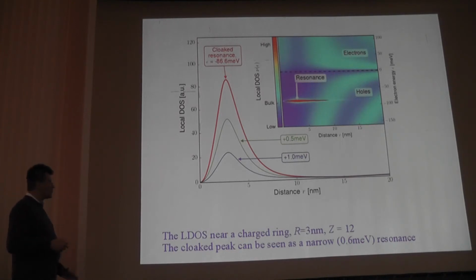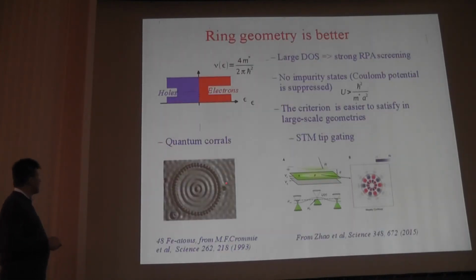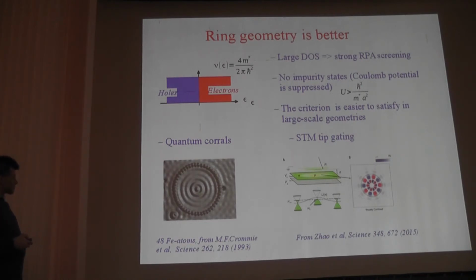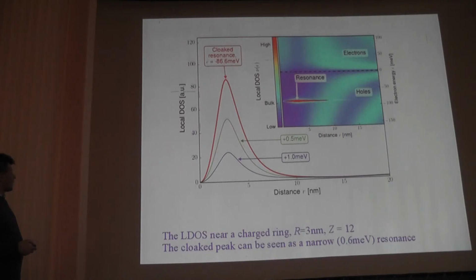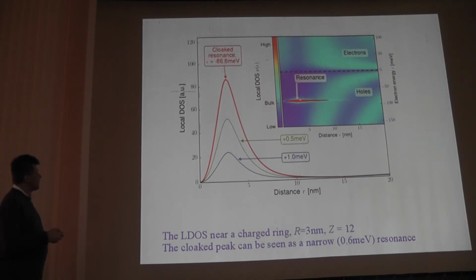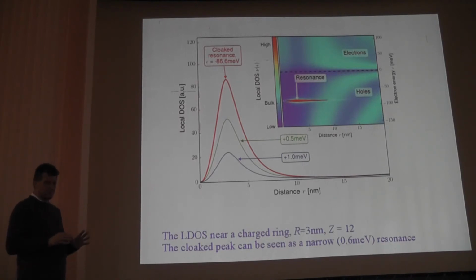Create a cluster of impurities, say in the form of a ring or a quantum corral, and probe the density of states in the vicinity of the structure. So then the density of states would look like this. Very close to the ring, you'll see a very sharp, less than 1 millivolt wide peak in the density of states, and that would be this invisible state.